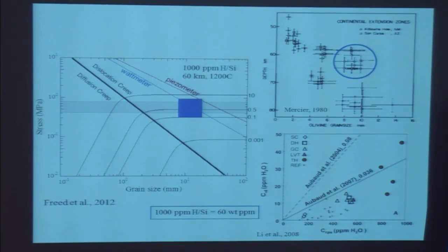The mantle background stress. Yeah. So this is the range of the mantle background stress that's being modified. One really important thing is that in order to see a post-seismic creep response, the change in stress has to be some sizable fraction of the background stress. So say the stress was 100 MPa and you change the stress by 1 MPa, you don't do anything. Part of what Andy is seeing is that in the lower crust, that's maybe what's happening. Maybe the stress is like 40 MPa and you change the stress by 1 MPa. So there's not a big effect.